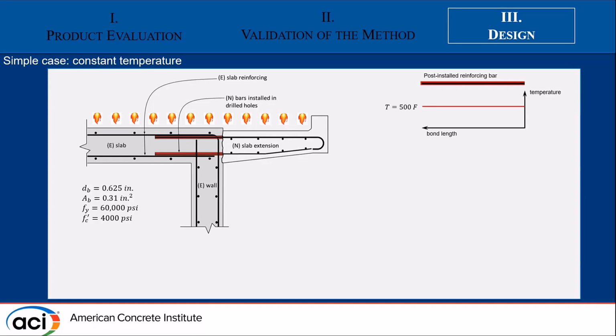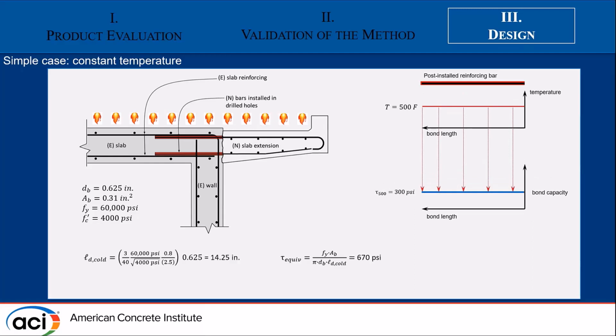So we have a couple of different cases. The most simple case would be if we have uniform temperature along the length of the bar, in which case you would have also a uniform reduction in the bond strength due to that temperature along the length. Then the calculation based on the development length, you can come up with an equivalent bond stress and have a relatively straightforward solution to how much longer your length needs to be based on the reduction of strength along the bar.